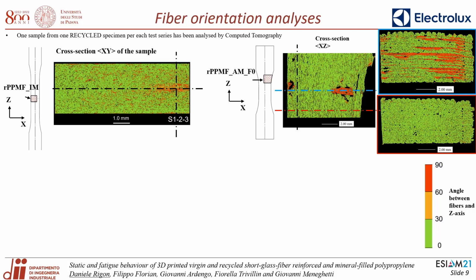It was our intent to not modify the G-code to avoid this problem, since these anomalies could occur even in a more complex component when the scan strategy is automatically generated. If instead we look at the cross-section on the gauge part of the specimen, see the section in red, it presents only fibers oriented between 0 and 30 degrees. This proves that the fibers are well aligned along the direction of deposition.